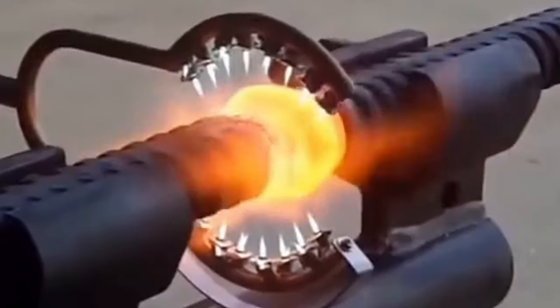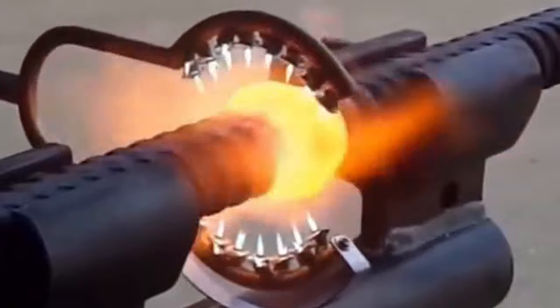Plasma welding evolved from TIG welding. The arc of TIG welding is not restrained. As current rises, the arc column diameter increases. The water-cooled nozzle restricts the plasma arc, preventing free expansion, and creating a high-energy, high-temperature plasma arc. It is similar to TIG welding, one has a high-pressure gunhead and the other does not. The plasma arc has a strong penetration ability and can weld a 10-millimeter thick stainless steel plate at one time.